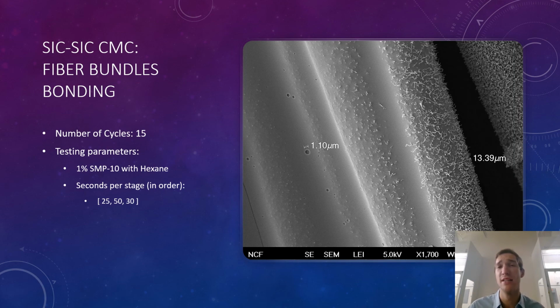Here we can see 15 cycles. There's quite a bit more interstitial matrix buildup. However, the matrix buildup is not delaminating from the fibers and is building up a fairly good matrix in between these fibers. I will talk about the almost fuzz looking material on the right hand side of the fibers in a moment.